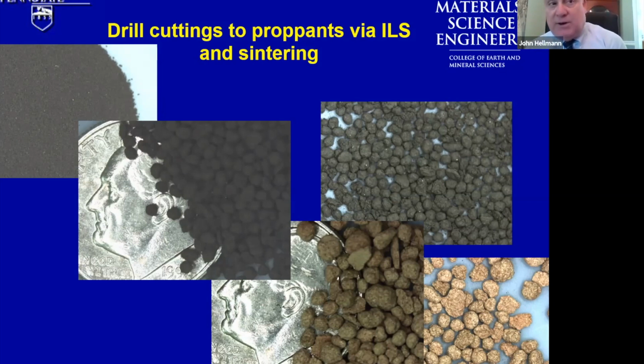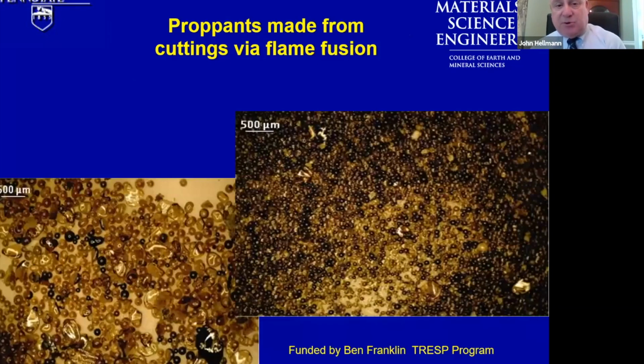More development means that we need to enhance the sintering kinetics. So back to our doped sintering studies from earlier in this presentation. And that's where the approach is. Because these are such high silica content compositions, we need to flux that silica to promote liquid phase sintering. But we can also flame spheritize these materials, as shown here. These are proppants made from drill cuttings after ionic liquid separation, aggregation, and passing through our flame tower. We're able to make quite uniform, highly vitreous beads, which subsequently, once devitrified, will perform like we demonstrated with the